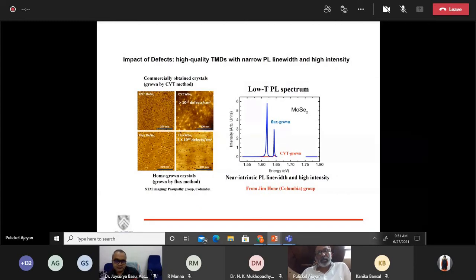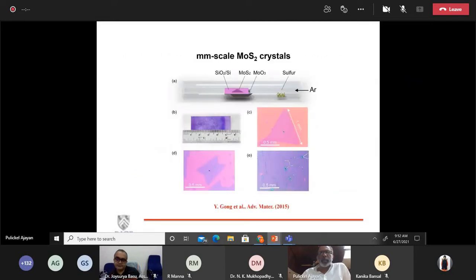It's also been proven, and again, this is a challenging area, that having defects can change the overall electronic properties of these materials. And it's not so easy to determine or control the number of defects that are present in these systems. Here is an experiment from the Columbia group showing that depending on the defect density in these materials, your electronic structure could be quite different. They have shown this by photoluminescence spectra, that an ideal PL spectrum comes from a material that has very few defects, which is kind of understandable. So there is another aspect to this. Again, to get consistent results, you have to go to larger grains or even larger-scale single crystal material. And many groups have shown that you can grow really large 2D single crystals without grain boundaries under the right conditions.